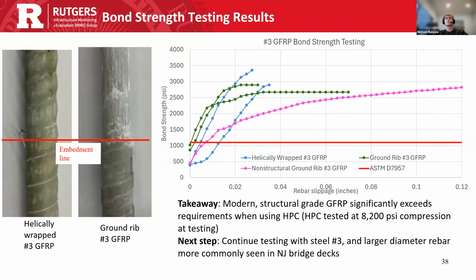You can see the actual structure of the rebar. You can see the ribbing or the helically wrapped structures that are commonly used in high grade rebar today, and you can see the embedment line. You can also see a little bit of difference in the behaviors. While both of them reach fairly similar peak bond strengths, a little bit of the behavior is different. Maybe ground rib holds that plateau for a little bit longer at the higher rate. But we'll further expand testing and get control samples with steel and larger diameter rebar with a modified setup.